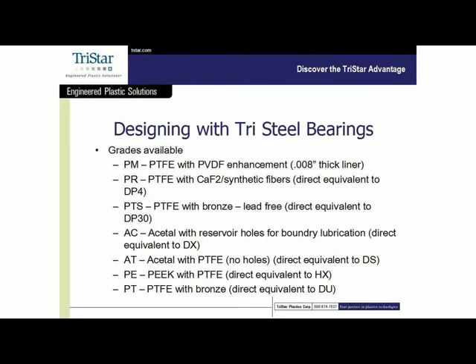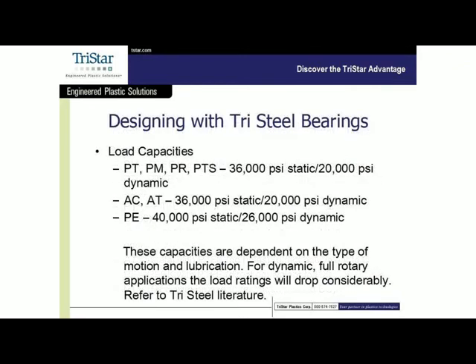Now let's take a look at some of the specific attributes of these different liners. First of all, load capacity, in terms of static and dynamic loads. For the most part, all the PTFE materials are about the same. They're 36,000 psi static and 20,000 dynamic. That's a good number for us to design around. With the acetal base, like the AC and the AT, it's 36,000 static and 20,000 dynamic for those as well. And then finally the PEEK, a little bit higher, 40,000 static and 26,000 dynamic.